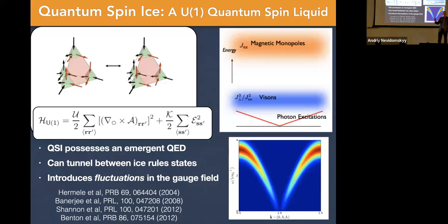And I'm going to do it a great injustice, but I'm going to say that the main thing that you get from the quantum spin ice problem that wasn't there in the classical spin ice problem is the ability to tunnel between ground states. So that's illustrated here, where we've got a little piece of the pyrochlore lattice, 4 tetrahedra. Each tetrahedron has 2 spins pointing in, 2 spins pointing out. But I've taken a hexagon of spins that connect these 3 tetrahedra here, and I've imagined simultaneously flipping all of them and tunneling from this ground state of the system to this other different ground state of the system. So quantum fluctuations can allow you that sort of tunneling.